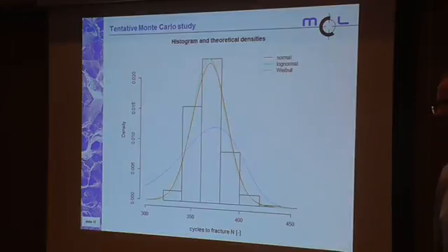What I did is I took this model, which at the moment does not yet include the distribution of the residual stresses. So all has been done for a stress ratio, load ratio 0.1, but with the scatter of the parameters as we have seen it. And then I did 1,000 simulations, and every time I threw the dice and got each parameter of the NASGRO equation, and then let the crack grow to the fracture of the specimen.